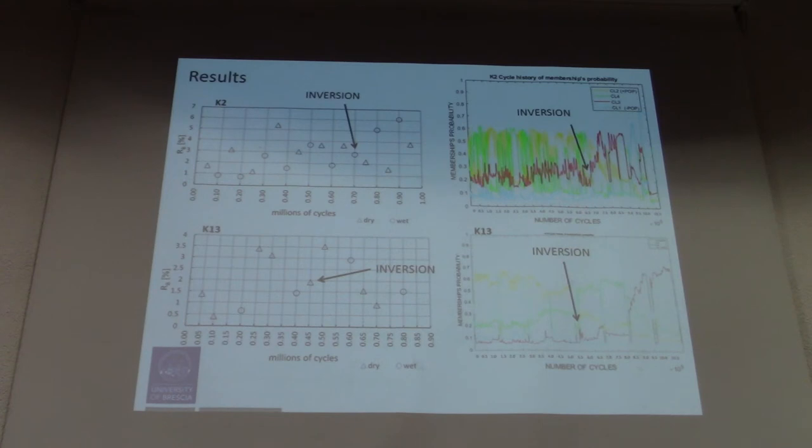For what concerns K2, we can see that the first inversion is at 0.7 million cycles. For what concerns K13, we can see that this inversion is at 0.45 million cycles.